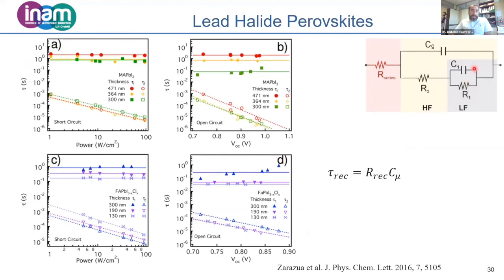You can also discuss the fitting results in terms of these characteristic times. This is the high frequency. You can calculate a characteristic time for the high frequency RC, so the product of Rg and geometrical capacitance, and also by the time constant of this RC as well. So in this work, they compare that the low frequency one is independent of the light intensity, and the high frequency one depends on the light intensity. Okay, so if you are interested in the results, these results are published here.